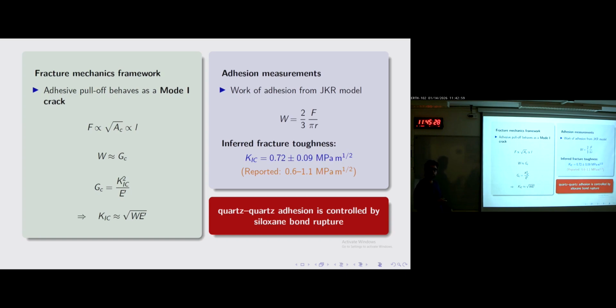That means that the force is really dependent on edge effects of the contact. We are detaching the nanoindenter tip from the contact at the edges, not all at once, but at the edges. We're kind of peeling it off from the edges. That's what we're going to learn from this scaling. And if you think about adhesives like adhesive tape, when you put it on the table and you start pulling on it, it doesn't come off all at once, right? It's always an edge effect, right?